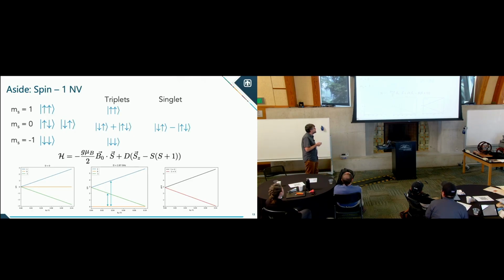Now the energy levels are defined by this Hamiltonian. So you still have the Zeeman interaction, but you also have this dipolar type interaction, D, which gives you a zero field splitting depending on the spin state. Okay, so if D is 0, the energy levels are pretty simple. For spin 1, you have increasing energy for +1, 0 Zeeman interaction for 0, and for -1, you have reducing energy.